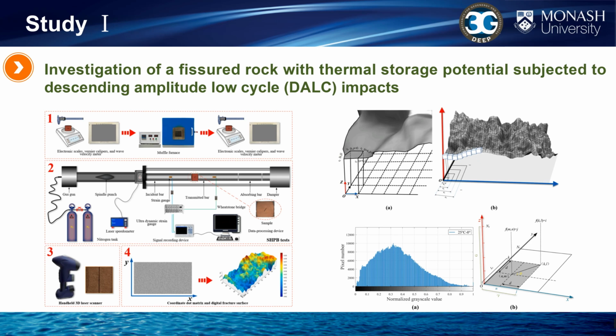The fractured surfaces are systematically characterized through an array of parameters, employing digital image techniques and statistical methodologies. Additionally, the analysis delves into intricate mechanisms of thermal damage and fracture evolution. This exploration leverages the mineral and thermal properties, DEM simulations, and strain energy density theory. Eventually, mathematical and statistical methods are applied to reveal the complex relationships between DALC mechanical parameters and the fracture surface features.